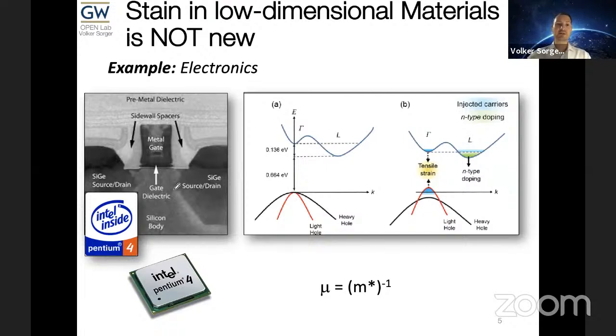Now, straining conceptually in optoelectronic devices is not new. We have been doing this for several years. This is Intel's Pentium 4 processor, 20 years old already. What they did is, for instance, here at this point, they basically strained the material so the light hole moved above the heavy hole such that we can have a higher mobility, because of course we all know mobility is inversely proportional to the effective mass. And this is addressing in silicon, for example, the low carrier mobility for p-doped and n-doped material.